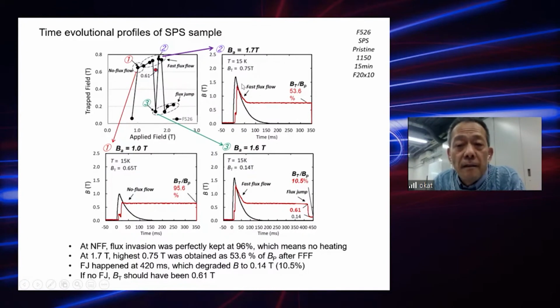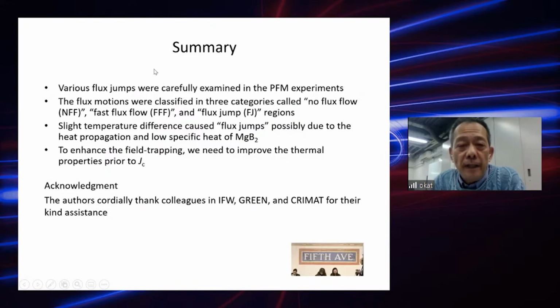So at 1.7 Tesla, the highest of 0.75 Tesla was obtained as 53% of the BP after this fast flux flow occurrence. So then the flux jump happened at 420 milliseconds after the flux flow like this. So then it is very, very lately shown. Which degraded the BT to 0.14 Tesla, which corresponds to only 10% of that. So if we can suppress the flux jump, the BT should have been 0.61 Tesla like this.